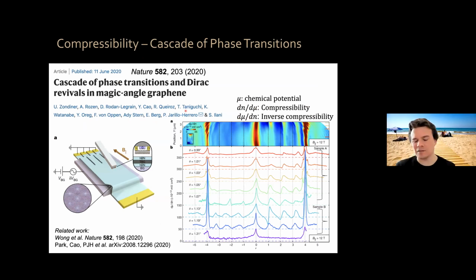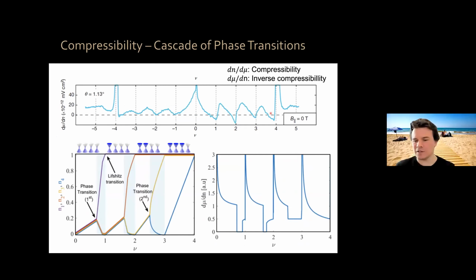In an interesting, collaborative work with my colleague Shahal Ilani at the Weizmann Institute, and very similar results were obtained by the group of Ali Yazdani using scanning tunneling microscopy. What we were able to do is the following. We took a scanning single electron transistor, a very sensitive electric field, voltage meter. And we were able to scan on top of magic angle graphene as a function of filling factor as we were changing the charge density. And what we saw in the inverse compressibility, d mu dn, is this sawtooth type of behavior and these peaks that occur close to all of these integers. Let me zoom in into one of these here.